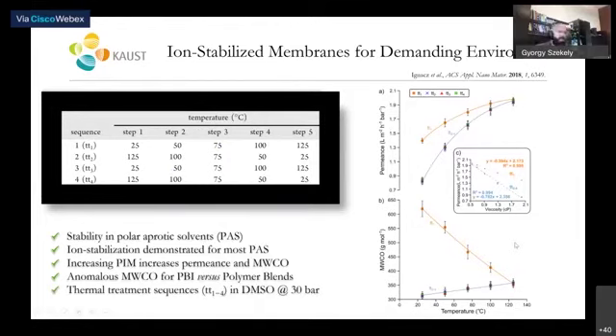Okay, so one of the other key aspects that is important for membranes is whether you can use them at high temperature or not. So what we investigated is the effect of temperature on these two performance metrics, the selectivity and the throughput. So here we did a sequence, actually 4 of it. We started with sequence 1, where we increased the temperature step by step. And then in sequence 2, we decreased the temperature back to room temperature. And again, we went up, and then we decreased back to room temperature. And here you can see the effect on the performance.